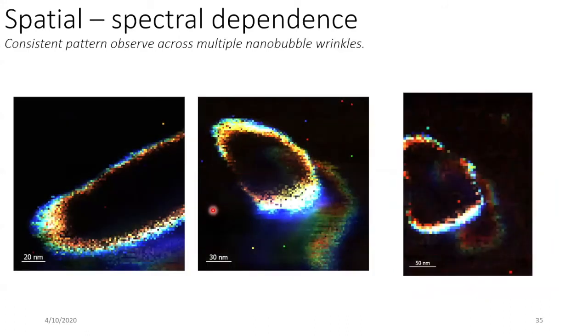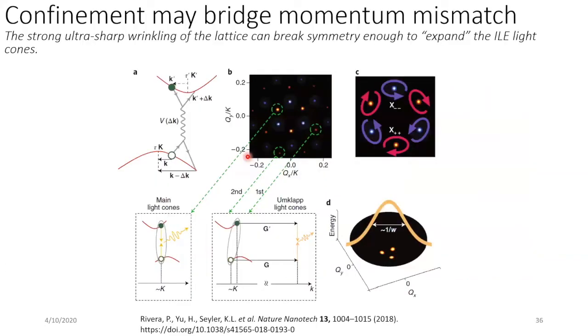So we can visualize that by integrating different bins and overlaying them, seeing what the color spectra looks like. Basically make an RGB-type image. Here I have a higher resolution scan of that same nanobubble. I'm going to choose three different color channels, energetically ordered: blue over here, green right here, red right here, and overlay the images. You get this rainbow-like structure in these nanobubbles. It looks like a lot of the interlayer excitons are more strained as you go toward the center of the nanobubble, and they're a little bit less strained as you're on the outside. You can ask if it's a similar pattern observed in the other three nanobubbles. From the two other nanobubbles I've gone through so far, it appears to be yes.